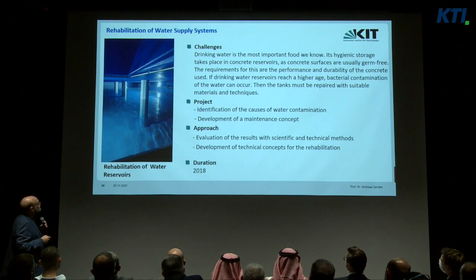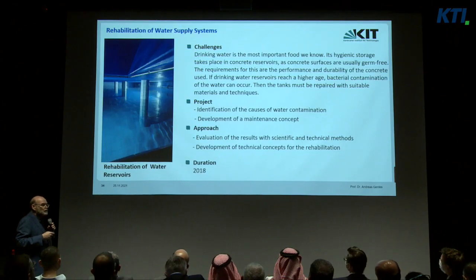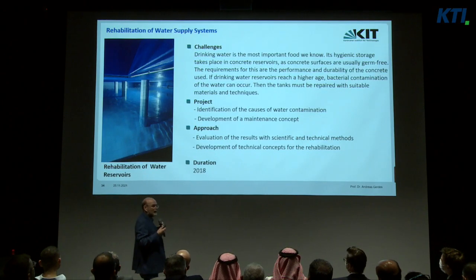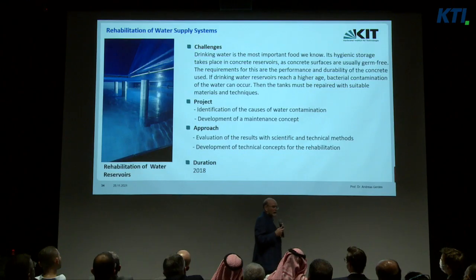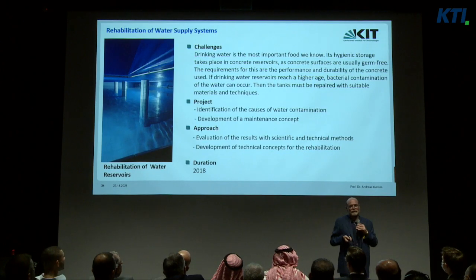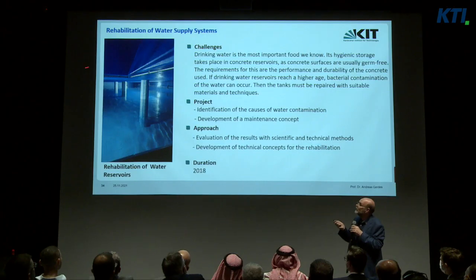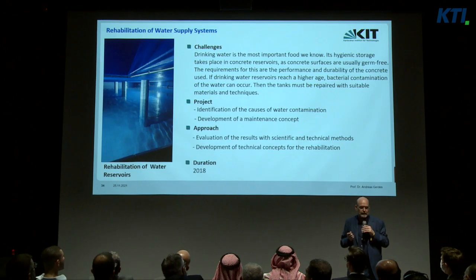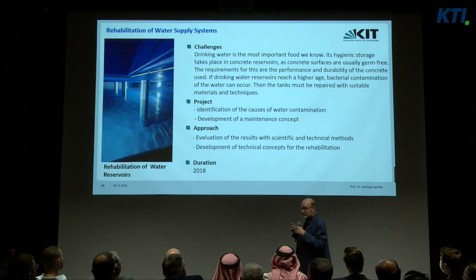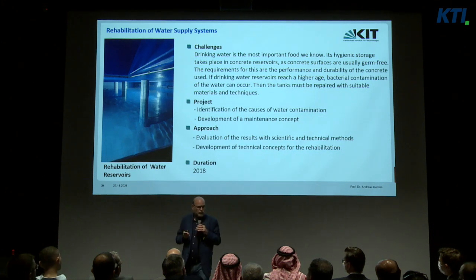Drinking water reservoirs. This is, of course, crucial for each human being, to have enough clear and good water. But it's very important to store this water, and therefore it's necessary to create new inner surfaces. I know that the British colleagues use epoxy resin for the protection of concrete in tap water reservoirs. In Germany, it's forbidden. It's not allowed because the risk is too high that biofilms are formed on the inner surface and will ruin the water. Therefore, it's not allowed.